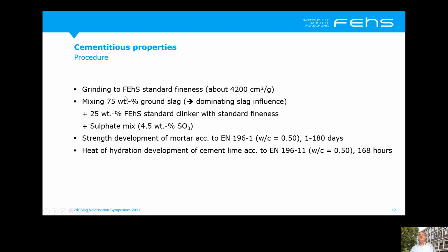To evaluate the cementitious properties, we normally use the same procedure. We grind the slag to our standard fineness, which is about 4,200 Blaine. We mix the ground slag, 75% of the slag with 25% of our standard clinker with the same standard fineness and some sulfates. We use this high amount of slag because then we can see the dominant influence of the slag and slag modification.